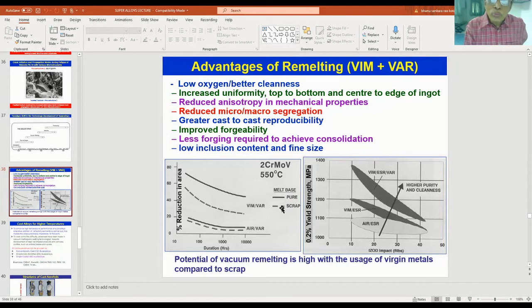You see, if you use pure virgin material for developing the superalloys, you see how much difference there is in melting of the scrap and melting of the pure virgin materials. The property of reduction in area gets dramatically improved by using the vacuum melting process. Nowadays, invariably, superalloys are processed through vacuum induction melting followed by vacuum arc remelting process.